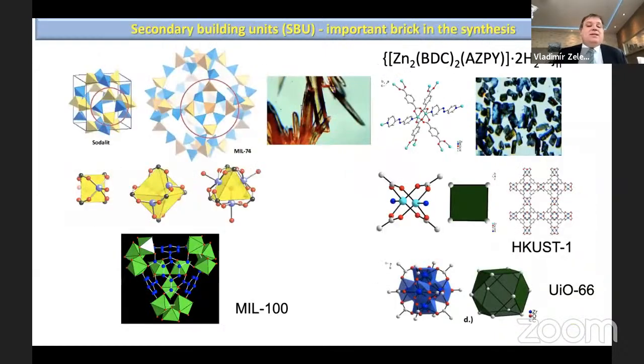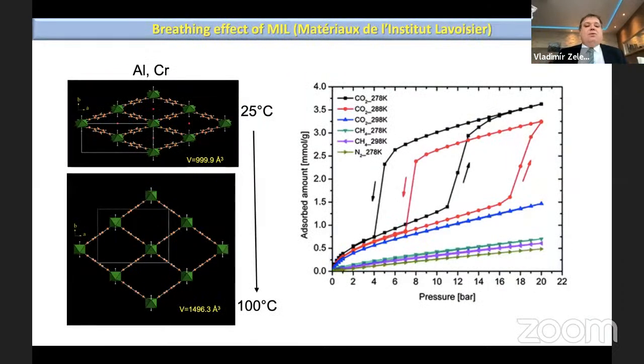In the synthesis of MOFs, we are also dealing with the synthesis of new MOFs. You have to look at so-called secondary building units. These are clusters of metal ions, which can be triangular, tetrahedral, octahedral, they can have different polyhedral shapes. And you connect these secondary building units with an organic linker, and you form the final porous structure. Such materials, of course, we characterize by relevant techniques, which I will show you later. And another property of these materials is that some of them have a so-called breathing effect. So the structure can open and close when applying temperature or pressure.